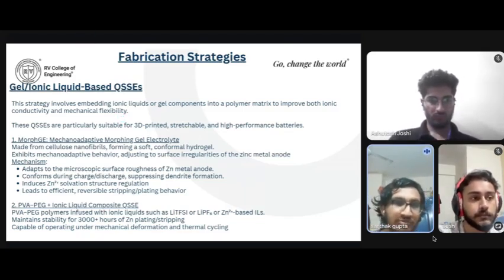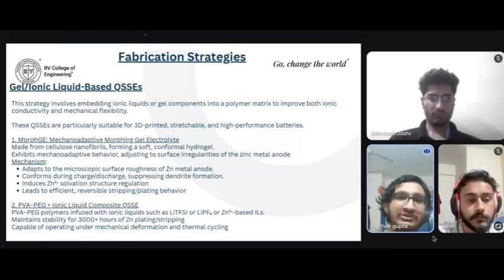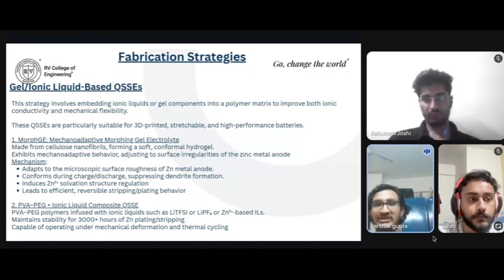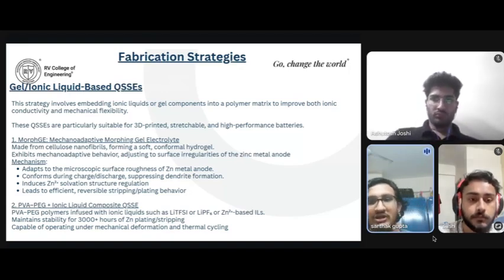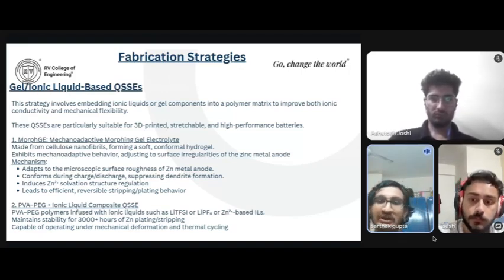So it consists of two parts, which are MorphGE and PVA PEG plus ionic liquid composite. MorphGE is basically a mechanoadaptive cellulose nanofibril gel. It is nothing but a fabrication involving a soft hydrogel that adapts to the surface morphology of the metal electrodes, such as zinc or some other metal. Then during cycling, MorphGE conforms to the electrode surface, thereby minimizing dendrite formation and maintaining ionic contact. This is critical for high current zinc ion batteries operating under deformation.